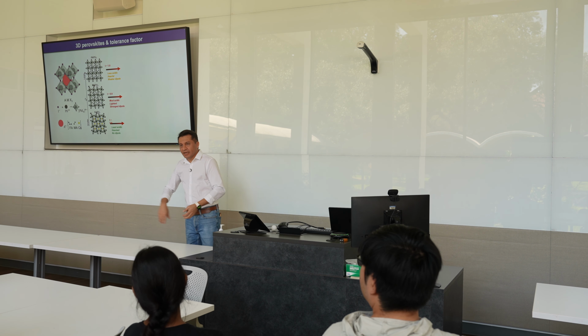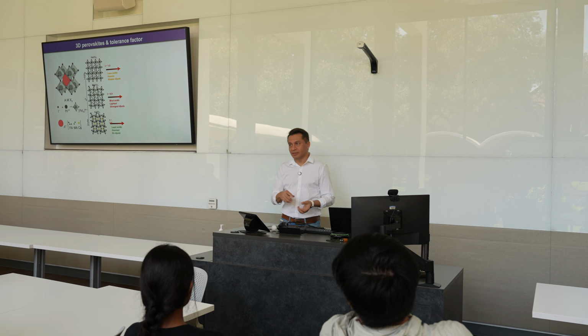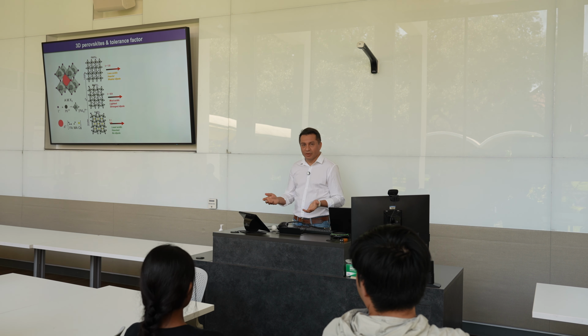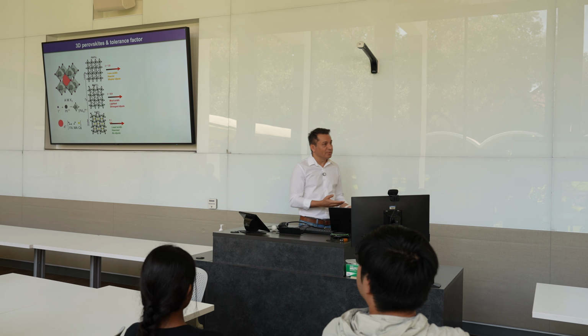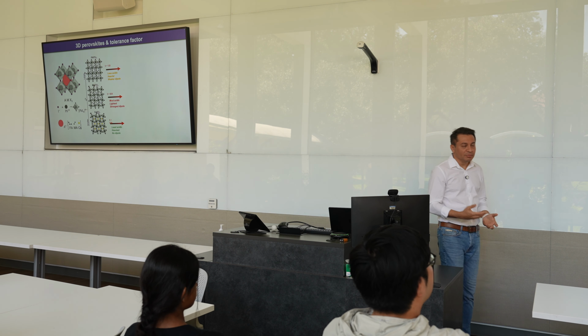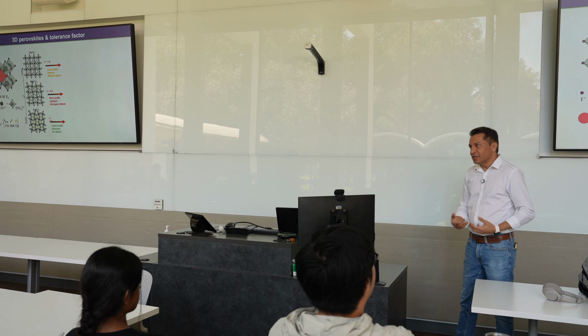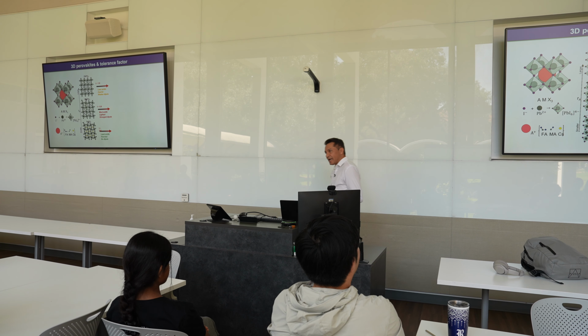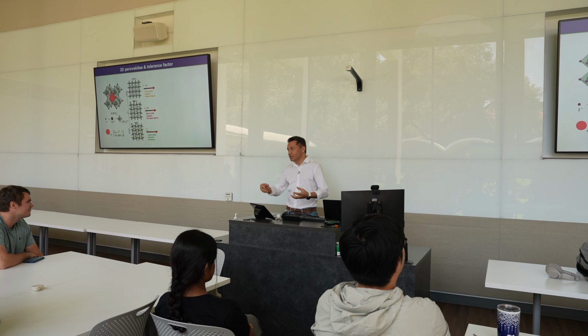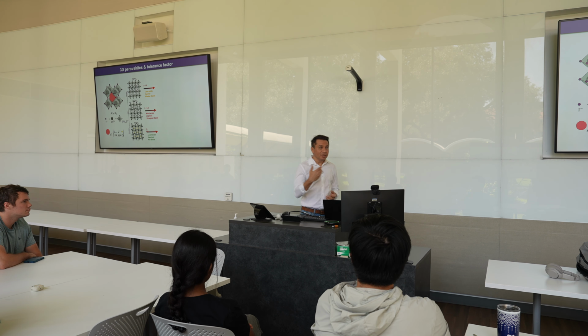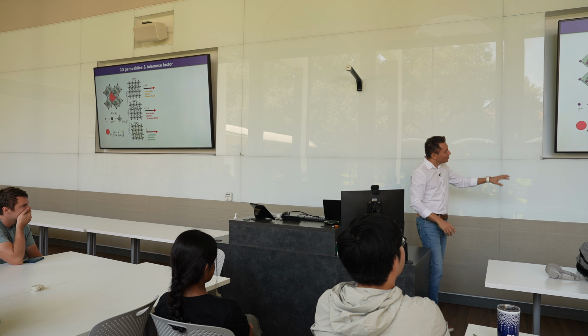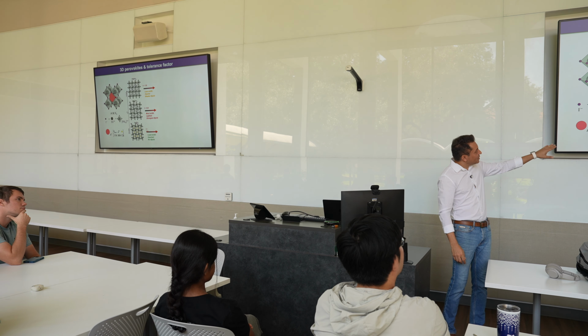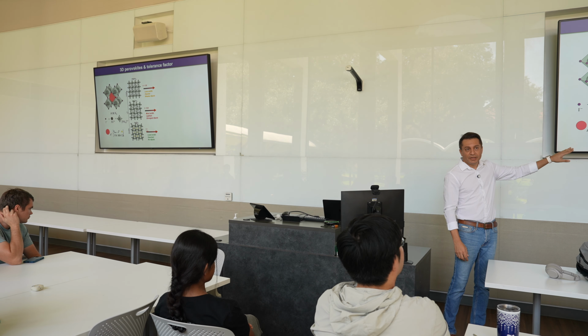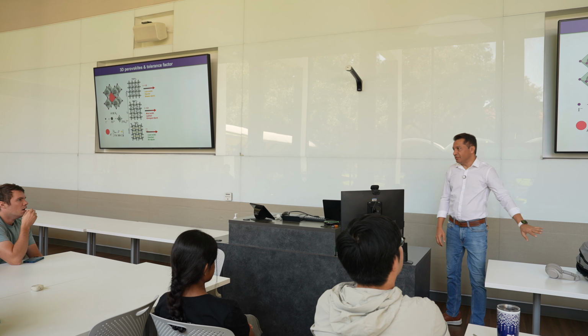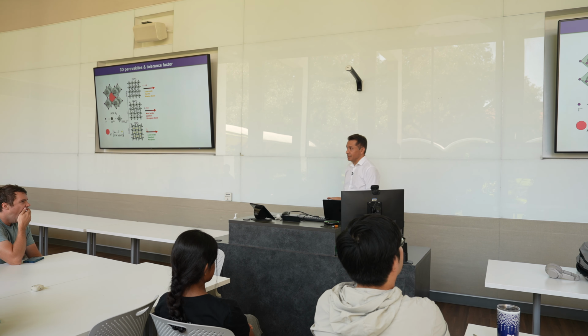So I take all these things, right, and I put them all together in a solution, and I make a film of these materials, right? How do I know if I've made a perovskite? Well, obviously, it depends on something which is known as the tolerance factor. Tolerance factor just comes from the fact that you have electrostatics, right, which govern everything because these are charged entities. And so everything in terms of the size and the charge has to fit together. And so if I take the ratio of all these ionic radii, there's a formula for that. It turns out that this tolerance factor, if it falls between a range of 0.8 and 1, then I get a perovskite phase. And if it doesn't, then I don't get a perovskite phase.